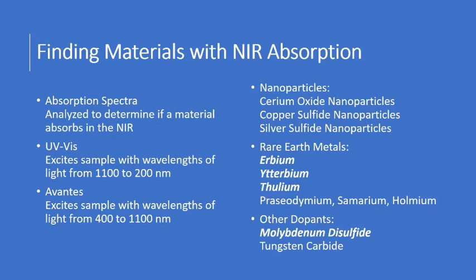We looked at three different categories from literature of things for near-infrared absorption. One was nanoparticles, one was rare earth metals, and the other was some various dopants. Out of the nanoparticles, cerium oxide, copper sulfide, and silver sulfide were what we tried. None of those actually showed any absorption in the near-infrared for our samples. But with the rare earth metals, we did see good near-infrared absorption in erbium, ytterbium, and thulium. Praseodymium, samarium, and holmium had good absorption peaks further in the visible spectrum, but not quite into the near-infrared, which is where we're looking.